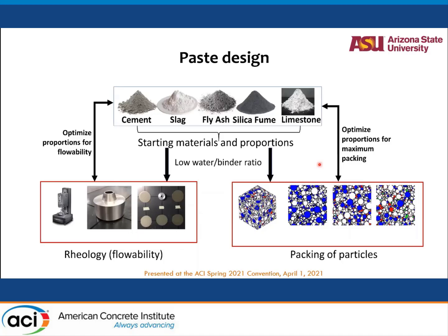So just to show you once more those materials, our idea was twofold. One, to take these combinations of materials in whatever order we want them for, and then do a particle packing approach to find out what will cause optimal packing, and then use simple rheological tests and come up with rheological parameters that can explain the rheological behavior, and in some fashion connect particle packing and rheology, which will form the binder design, and of course check the reactivity using isothermal calorimetry and make sure that the combinations that we have selected are not detrimental in terms of early age properties. So that was our first part of designing the paste, which I'll go through.